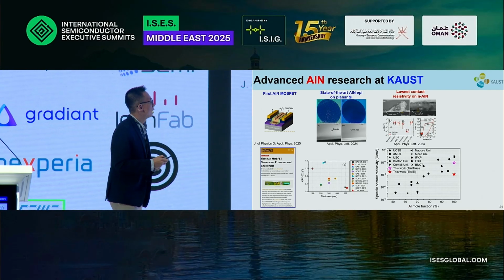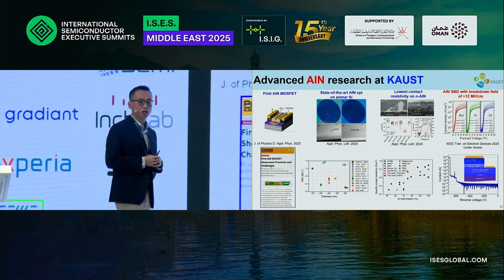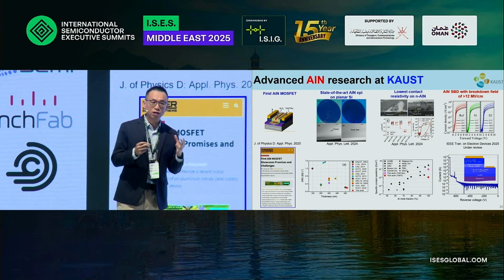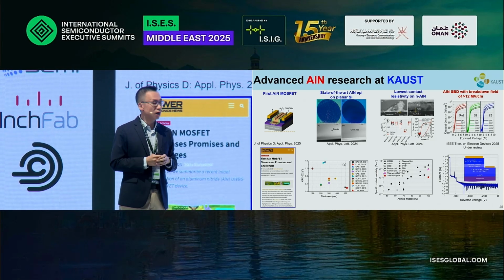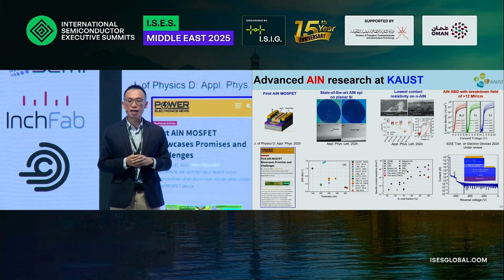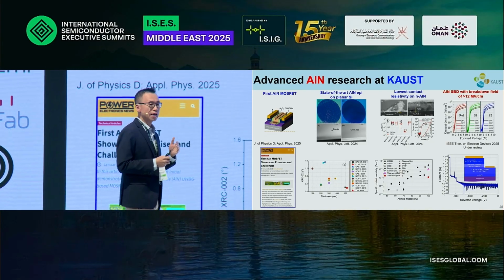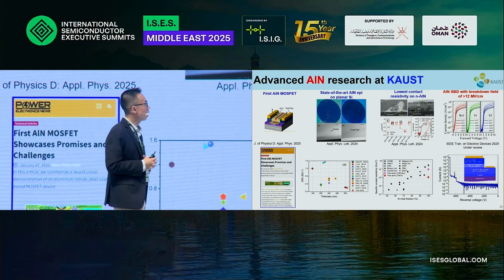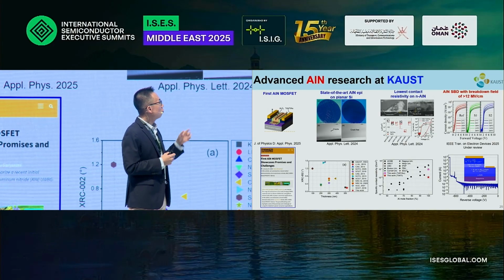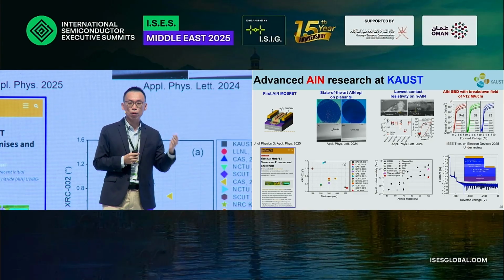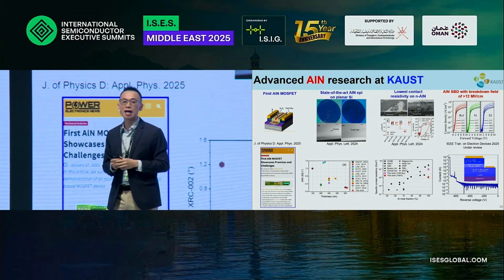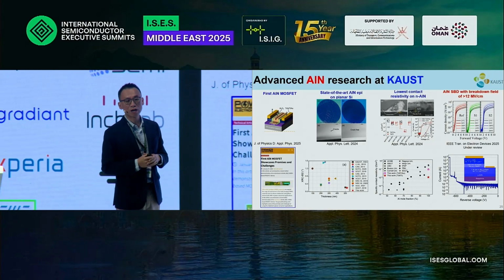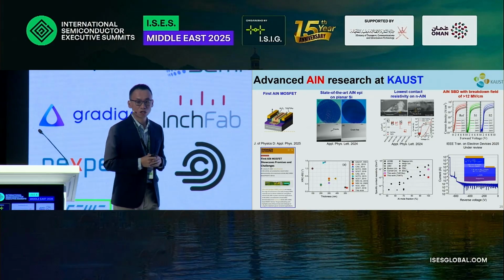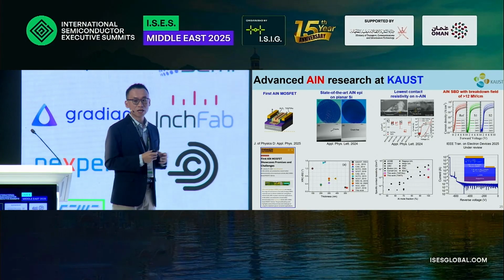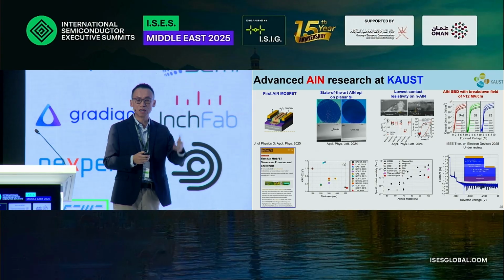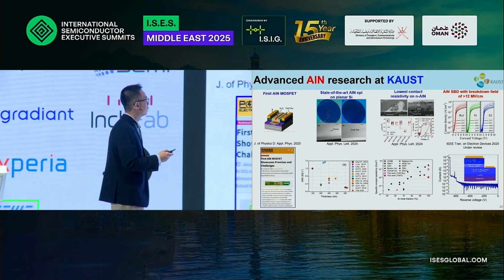The last work that we have achieved recently is on the breakdown, right? For silicon carbide and GaN, the breakdown is a couple of megavolts per centimeter or so. But when you switch from GaN and silicon carbide to aluminum nitride, in our work we have realized an aluminum nitride Schottky barrier diode with breakdown over 12 megavolts per centimeter. This is one of the records for breakdown in power semiconductors. Those are still early studies, and we hope to continue to develop aluminum nitride-based power electronics technology.